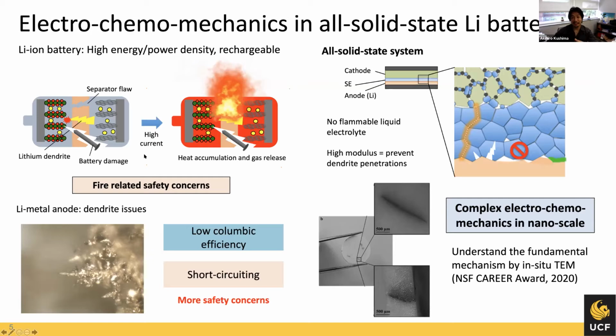And if you want to extend it further by using lithium metal batteries, you will create these dendrite issues. So the new technology is to use an all solid-state system that uses solid electrolyte instead of liquid, so that can prevent the lithium dendrite from going through the electrolyte and reaching the other side. But still, this solid electrolyte causes issues because a lithium dendrite can penetrate through the grain boundaries and reach the other side, just like this, showing these images here.